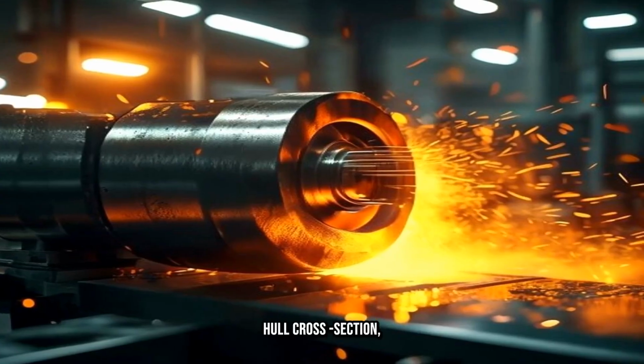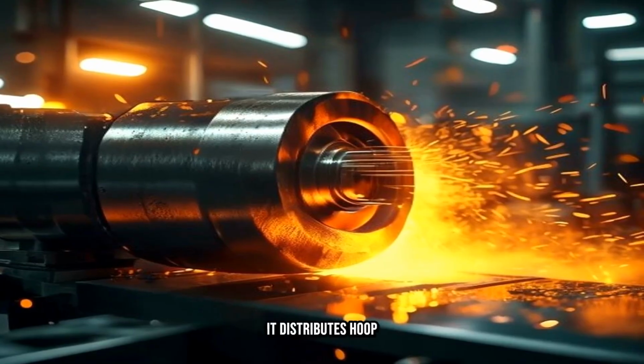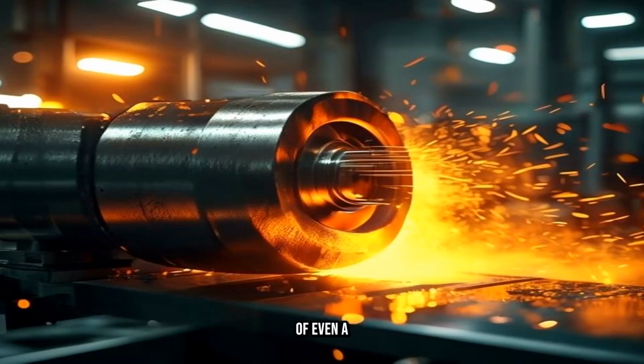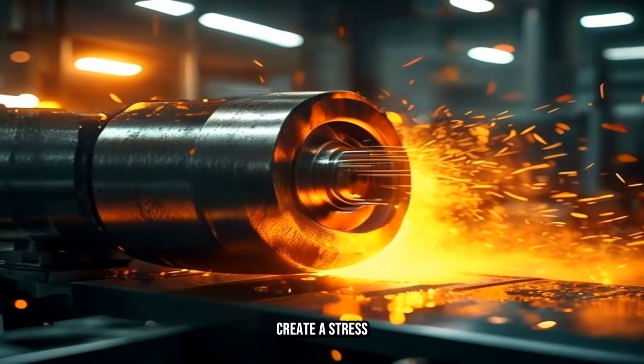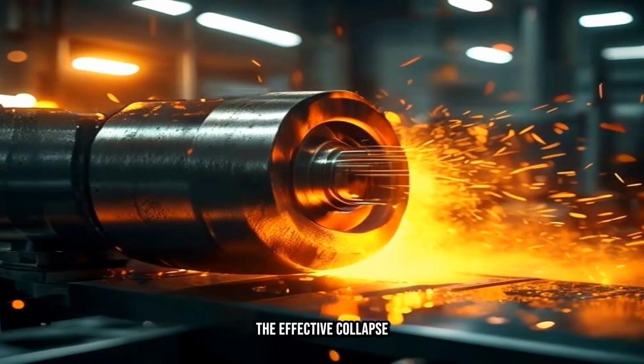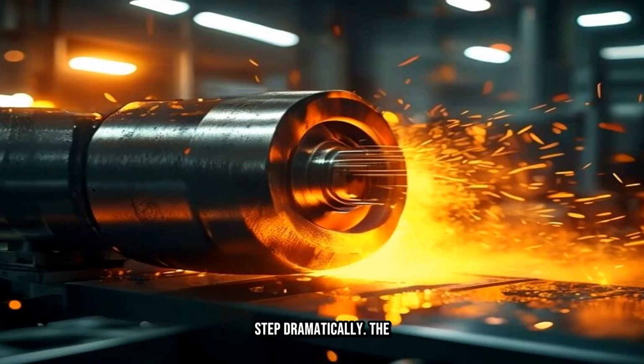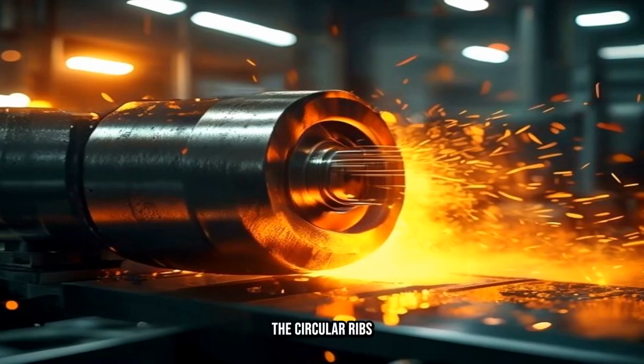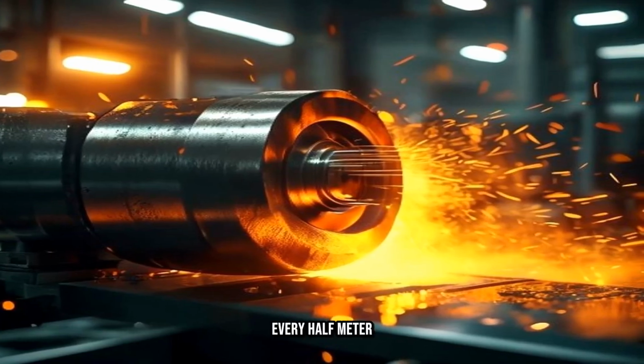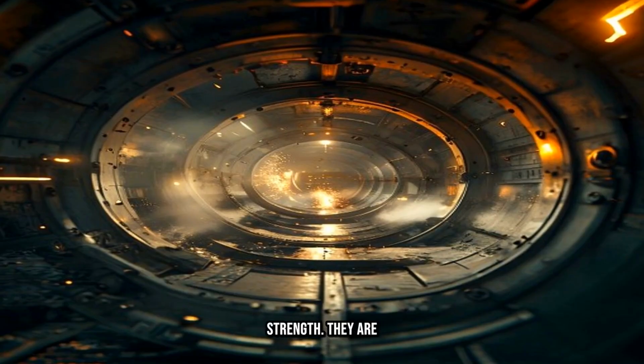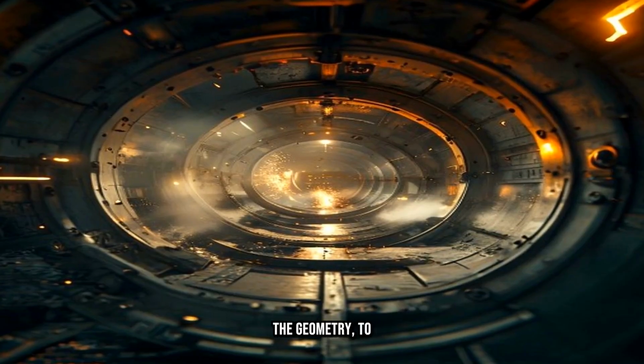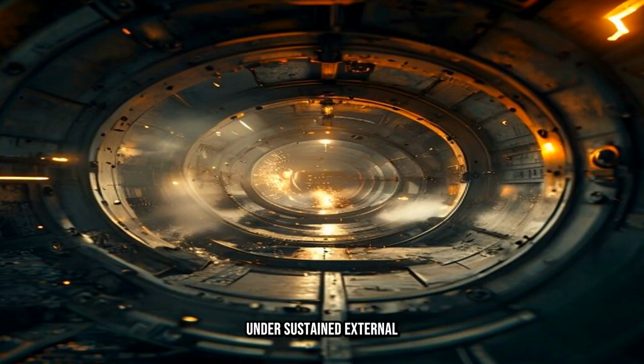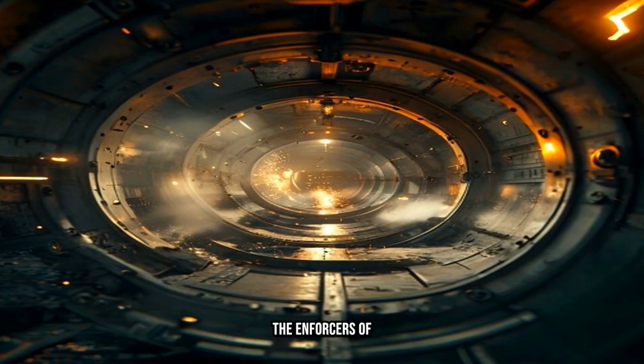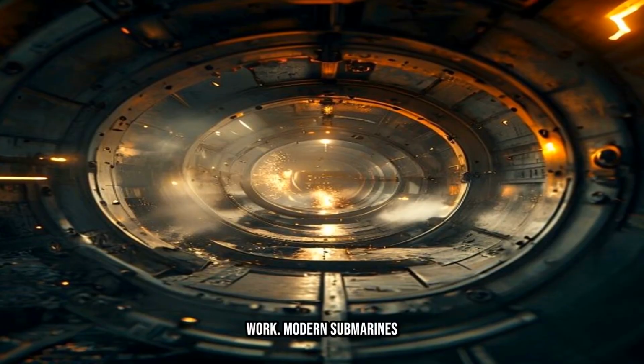The rounder the hull cross-section, the more perfectly it distributes hoop stress. A deviation of even a few millimeters from true circular can create a stress concentration that drops the effective collapse depth dramatically. The internal ring frames, the circular ribs that run around the inside of the pressure hull every half meter or so, are not there primarily to add material strength. They are there to maintain the geometry, to enforce the circle and prevent the gradual ovalization that would otherwise occur under sustained external pressure. They are the enforcers of the shape that makes the physics work.